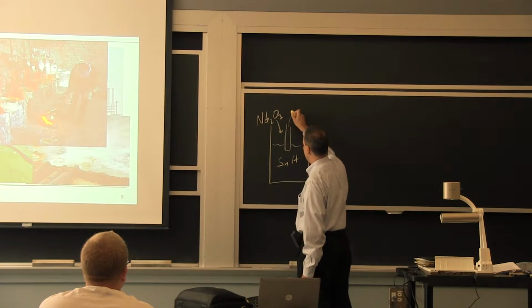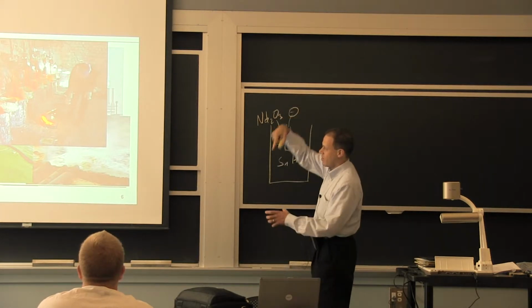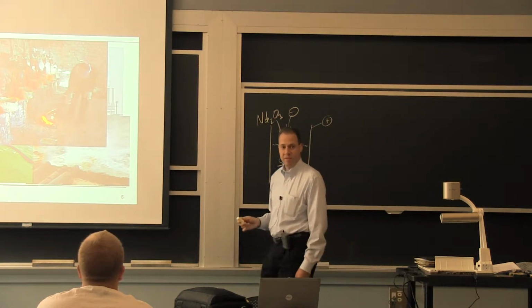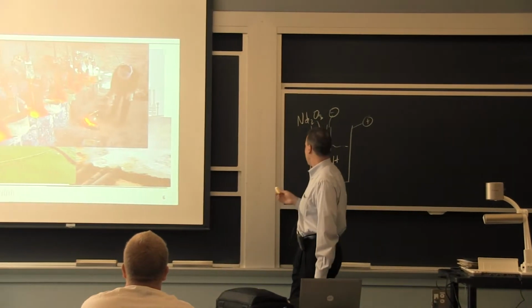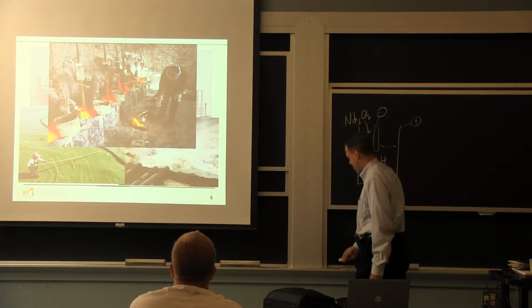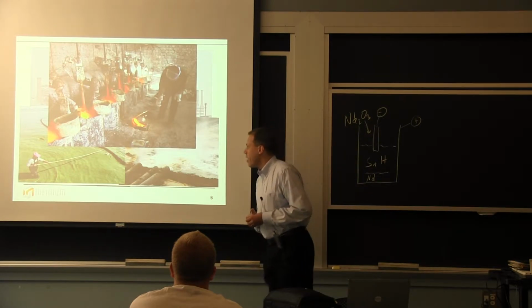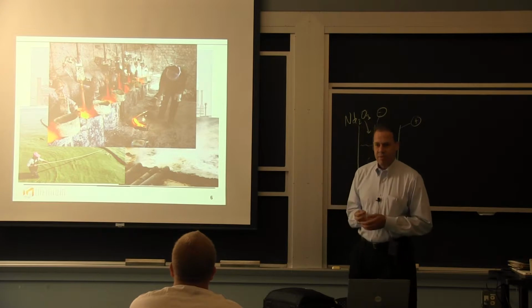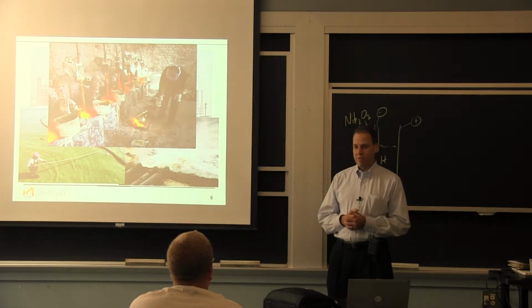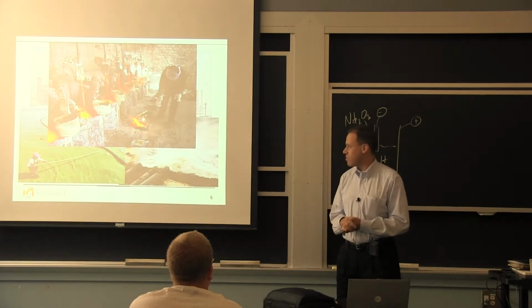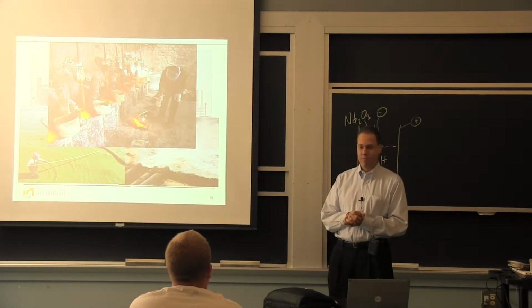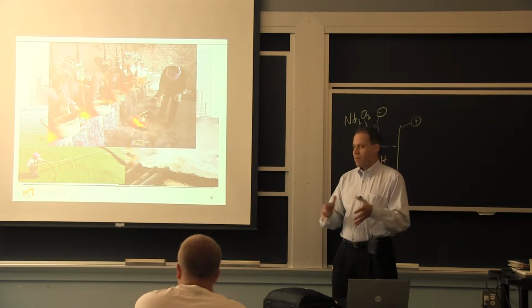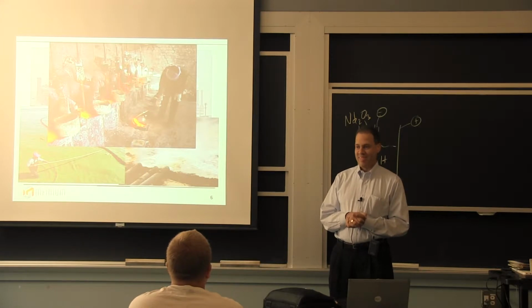And you put into it some kind of a cathode. In this case, they use tungsten. You can see the tungsten cathodes down the middle. And an anode. In this case, they actually use the entire graphite vessel, and they make a little bit of neodymium metal in the bottom, and then harvest that with, in this case, a molybdenum ladle. And the only anode technology that people can get to work with this is graphite. And carbon is a contaminant in neodymium. It reduces the magnetic performance. It's a diluent for the magnetic performance of the magnet. So you're making this in a graphite vessel with graphite anodes. You're going to get some carbon in it.